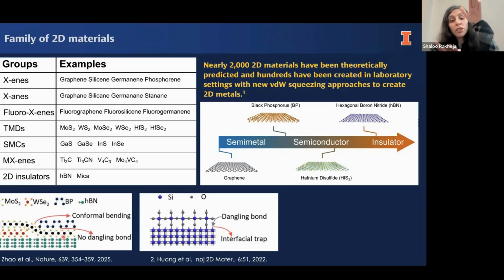Now, one of the advantages that people often tout for these 2D materials is the ability for us to stack these different materials on top of each other. 2D materials have very strong covalent bonds within the plane, but out of plane, they have van der Waals interactions. So these materials naturally do not have any issues related to the mismatch of the lattice between the different materials. So it gives us the possibility to integrate many different kinds of materials with very strange electronic properties and even optical properties. This doesn't really happen in the case of 3D materials, because 3D materials do have lots of problems with interfaces. They develop dangling bonds, and they develop interfacial traps. So you can think of 2D materials as naturally passivated in the third dimension. So you can really put these materials on top of each other.